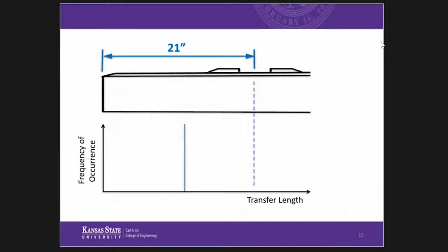We really need to stop thinking about transfer lengths as a single value, but rather there's a distribution, right? It's a histogram. And we've actually gone out to plants and measured, I think we measured 150 in one day, and you actually calculate a mean and a distribution. And if we were to test these ties in the AREMA test, they're all going to test the same value. Okay. Likewise, if we had a histogram with a longer transfer length, chances are if we tested these ties in a flexural test, we're going to get the exact same result.